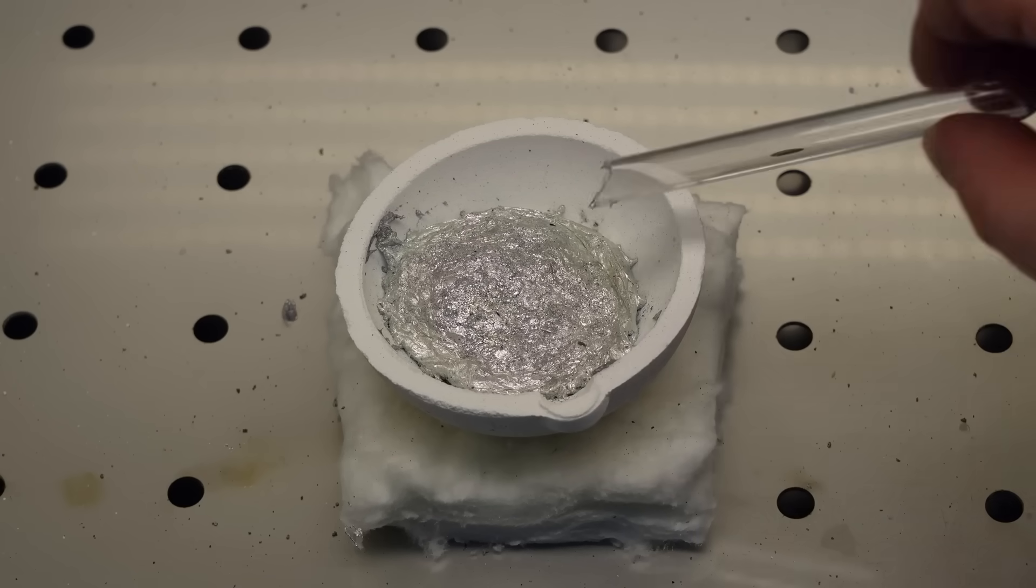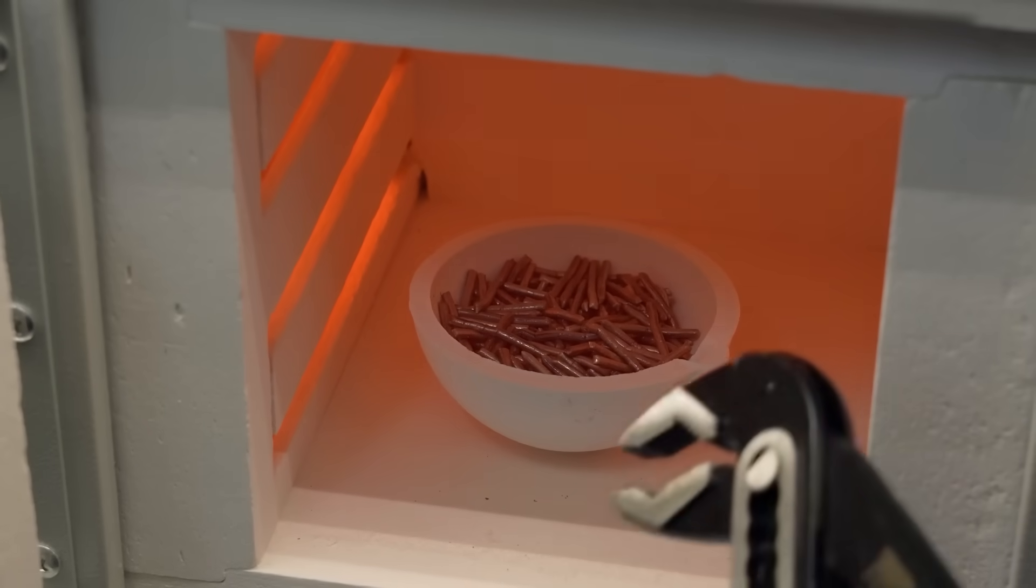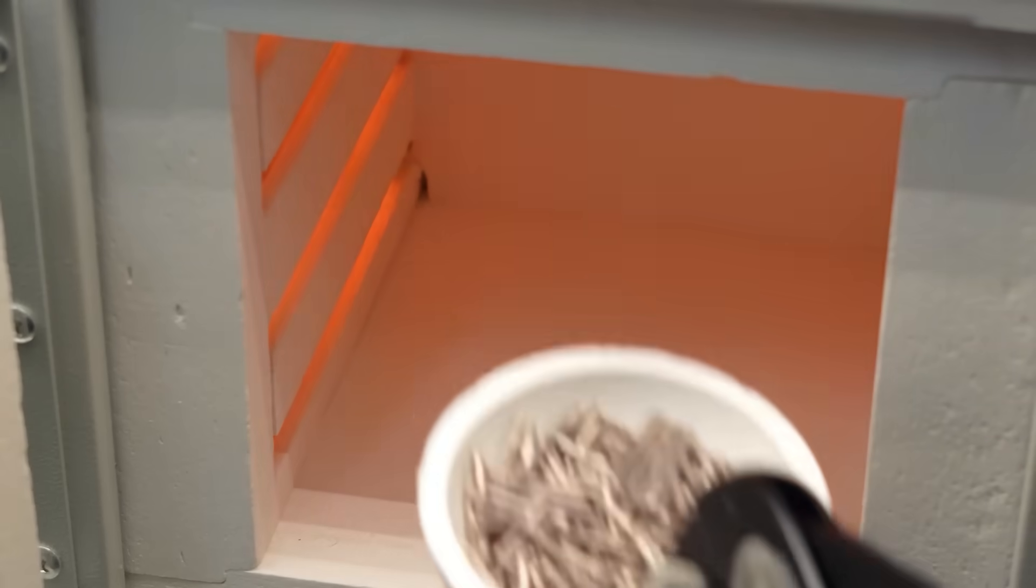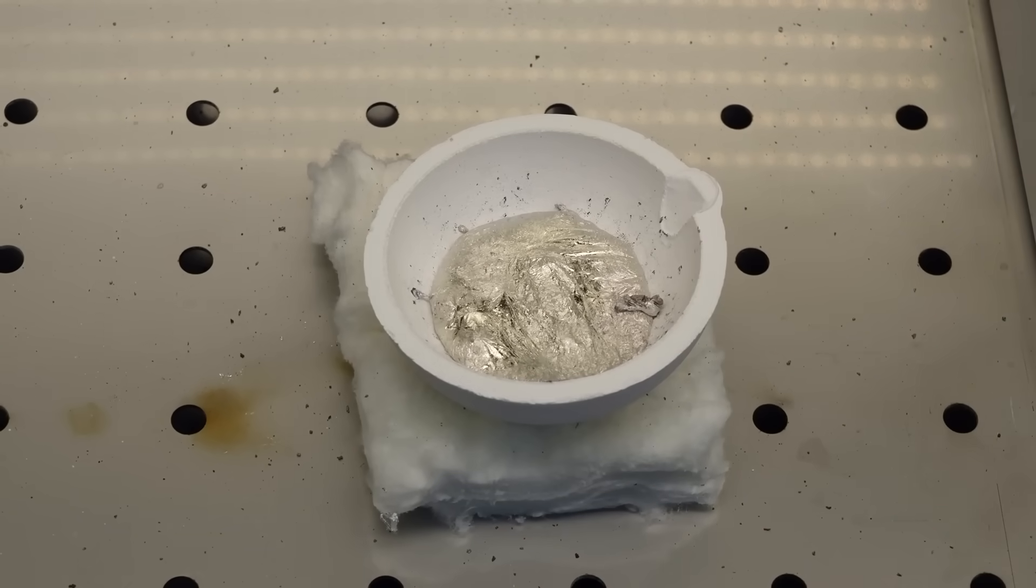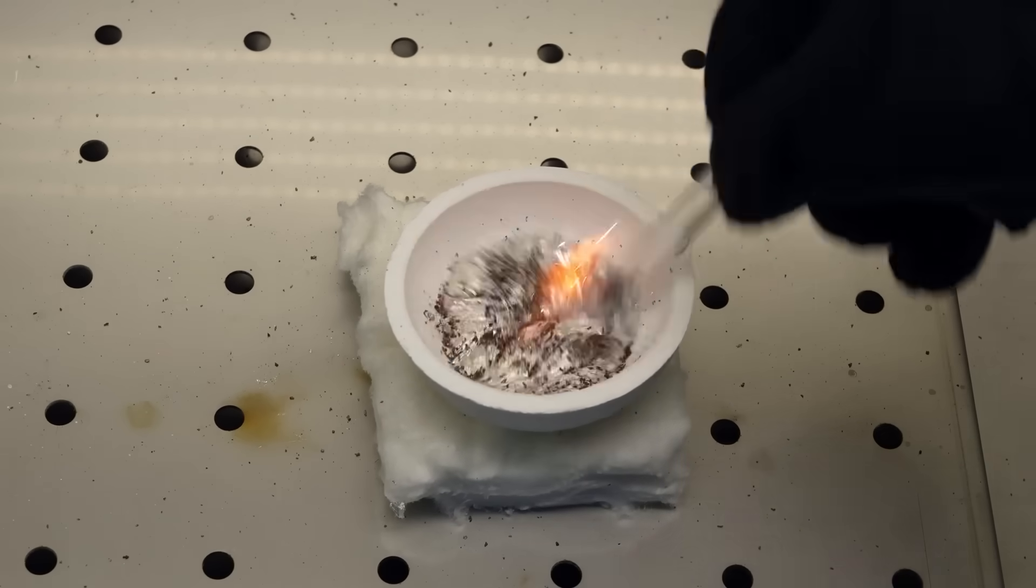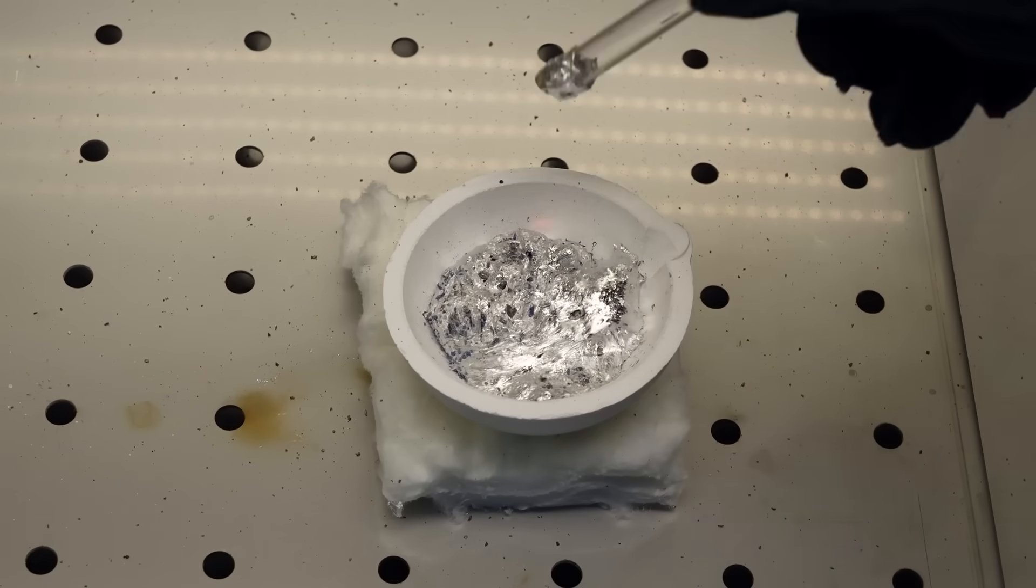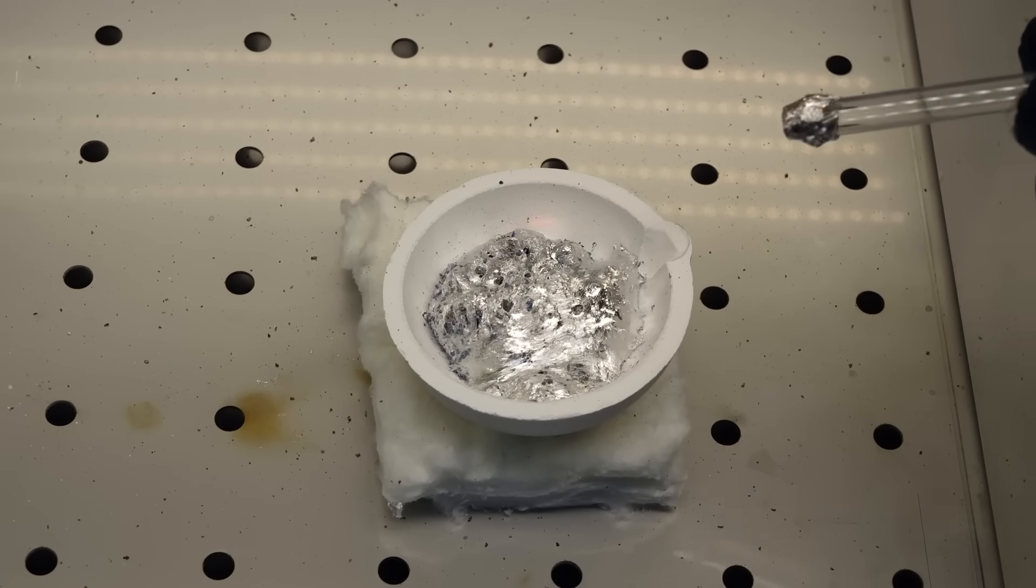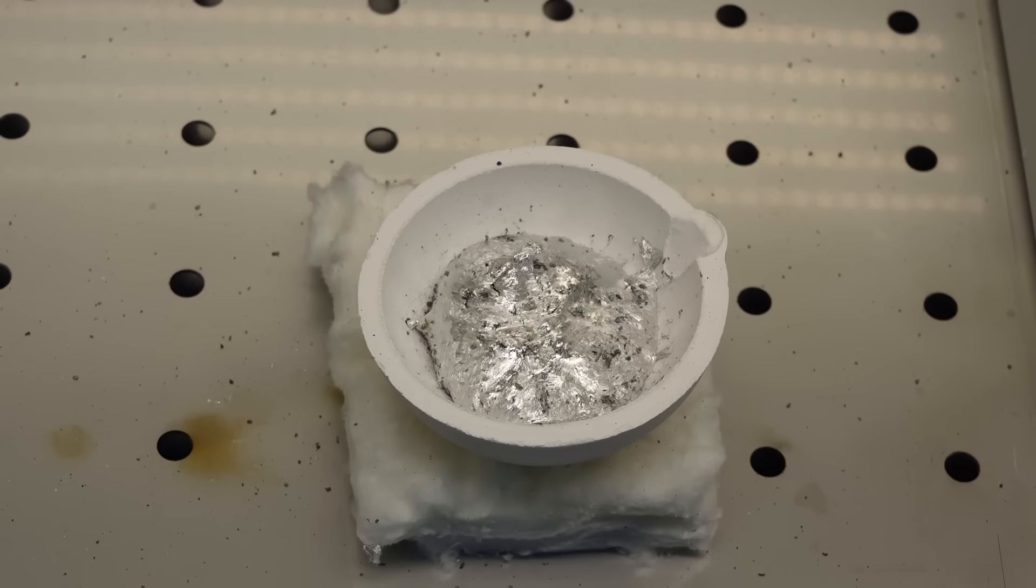As you can see, it started to instantly decompose into titanium and hydrogen. So, using a quartz tube, I'm trying to quickly mix it into the molten aluminum, so that it foams the metal with the hydrogen that's being released. According to the instructions, I need to keep stirring the alloy until the metal is saturated with hydrogen and solidifies.